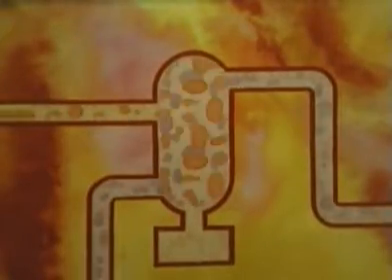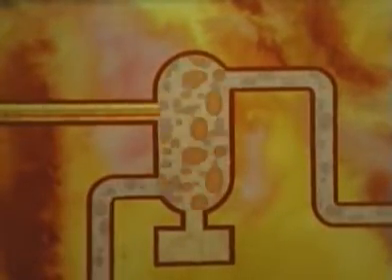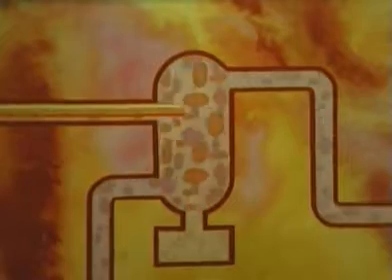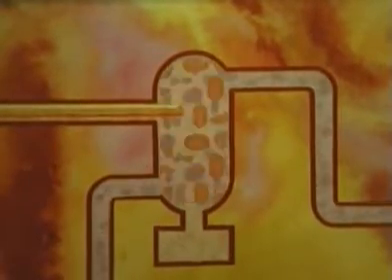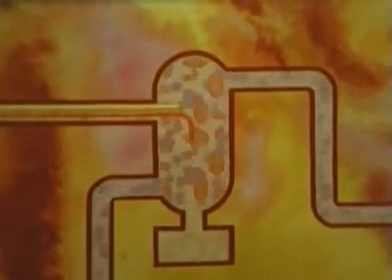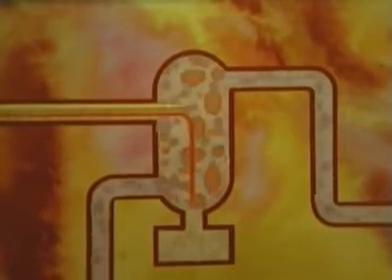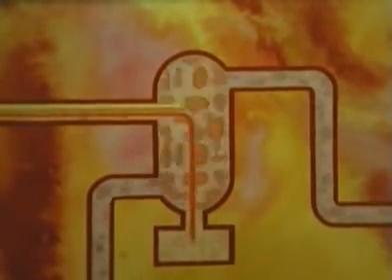The uranium and plutonium nitrates in the solution form complex compounds with TBP, and these compounds are to be found in the organic phase. On the other hand, the major part of the fission products remains in the aqueous phase and is discharged from the column to be first concentrated, then stored.